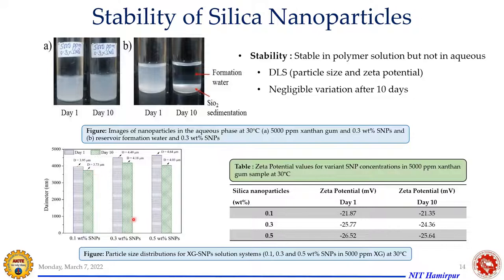Even as we keep increasing the nanoparticle concentration, 0.3 to 0.5, from day one to day 10 the variation in the nanoparticle size is pretty small. So you can see these are stable when we measure the average diameter of the solution after a certain duration, that is day one and day 10. This says it is stable. We have also done the zeta potential analysis, and negligible change in the zeta potential was shown. So we can see these are stable.